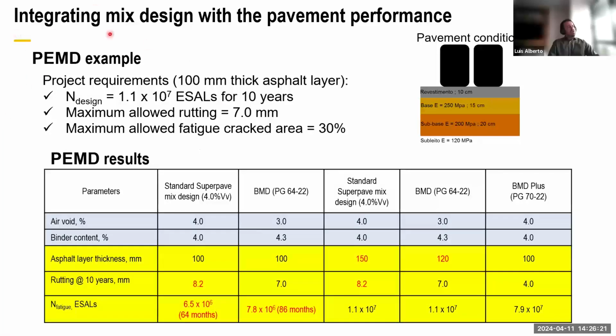This is an example of how we can integrate the mix design with pavement performance. We have a kind of typical pavement here and some project requirements. We have 10 centimeter asphalt layers, a design traffic level, and a maximum allowed rutting of 7 millimeters and 30% of cracked area. Looking at the results of the performance-engineered mix design, you can see the Superpave mixture, the typical not optimized one, with 4% voids, didn't meet the minimum required. We have a higher rutting when compared to the limit, and a shorter fatigue life when compared with the design.